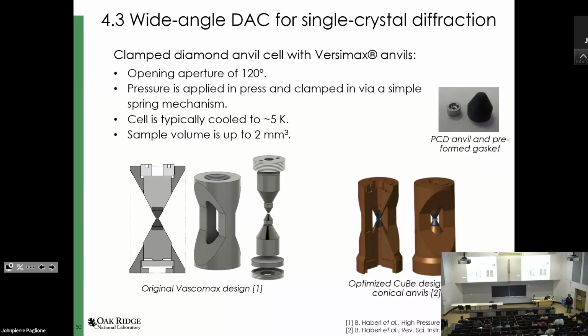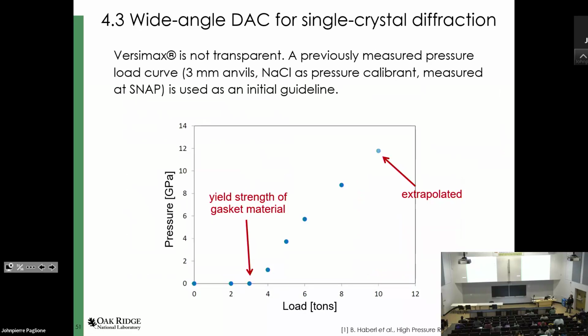because of course as you cool things, things expand, things shrink, or when you change temperature. And you do not want any of these changes affecting your pressure. So these ones here have been quite stable on cooling to 5 Kelvin. For these cells, we also have some pressure load curves that we can use as a guideline. I would not say this is what your final pressure is, but you want to have a rough idea of what you are shooting for before you actually start pressurizing.